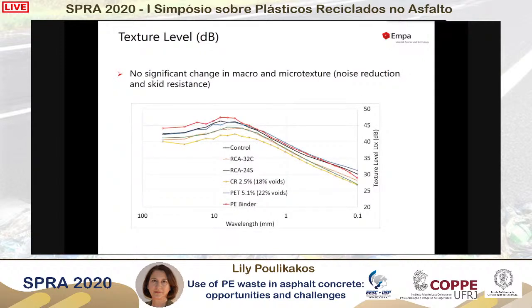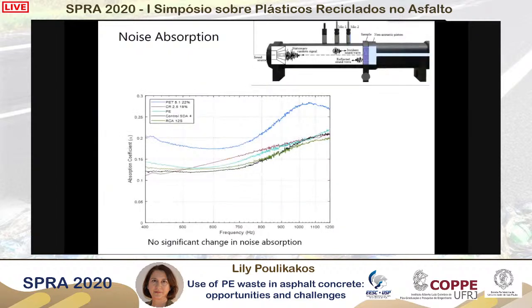And so in our project, we're looking at various types of mixtures, not only the PE mixture, but here you can see a whole range of them. The PE mixture is shown in red, the control polymer modified is shown in black, and you see that in the region that is important for noise, we don't see a significant difference between the reference and the PE modified mixture. So as far as surface texture is concerned, we are not at a disadvantage.